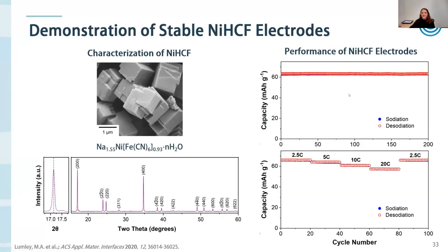And another thing that we looked at is the effect of the rate of charging and discharging on the performance of our nickel hexacyanoferrate electrodes. So this is a really common practice in electrochemistry. You can change how fast you run your reaction, and that typically has an effect on the salt removal capacity. And what we saw here is that when we cycle our electrodes for 3 minutes per cycle at 20 C, we see almost the same capacity as when we cycle them for 25 minutes per cycle. So this is really encouraging and indicates this fast kinetics for sodium insertion and sodium release reactions that is important when we're trying to produce desalinated water on a commercial scale.